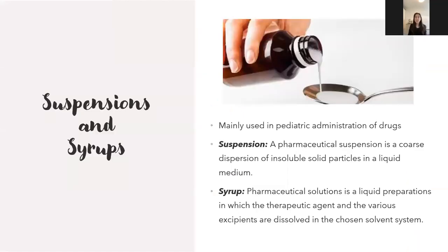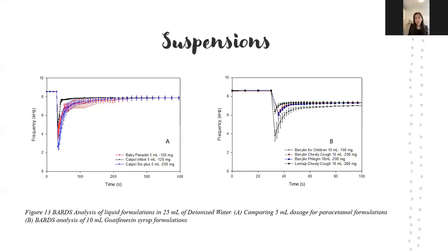Our last type of formulation is liquid, and we're going to look at suspensions, which have the API remaining in the liquid undissolved, and syrups, which are cough medicines. Typically, they are used as cough medications, and they have the API dissolved. On our left, we see the comparison of paracetamol containing formulations of different dosages, and they are 5 ml dosages, and the Panadol Baby and Infant have 120 milligrams in the 5 ml, and the Calpol 6 Plus is 250 milligrams. But they all perform relatively similar.